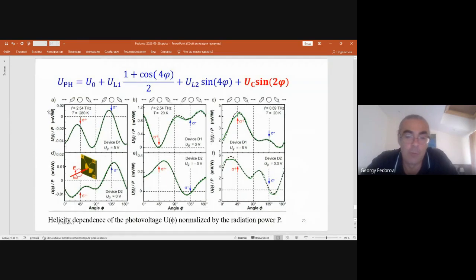As for the response that we measure, just connecting the voltmeter to the source and drain electrodes, it turns out to be composed of two contributions. One is pi over 2 periodic, the other is pi periodic, and you can actually remove each of them by changing the gate voltage or temperature. So here is a wider set of data illustrating what I've said. And the most impressive thing you can see, for example, is that for clockwise and anti-clockwise circularly polarized light, you see the change of sign of your response. It's impossible to imagine for any standard rectification mechanism. So it actually signals that the response is to a significant extent defined by the plasmons excited in the channel and interfering inside.